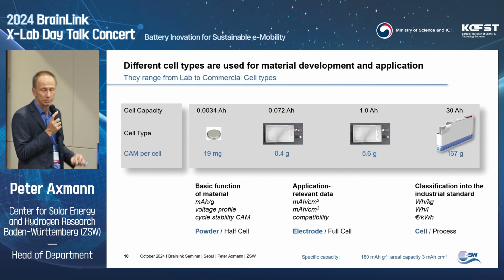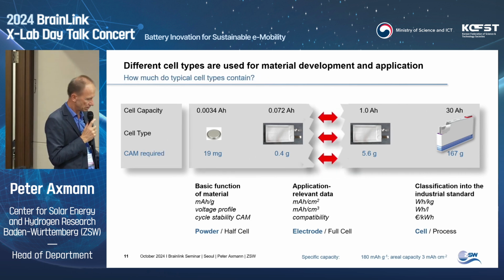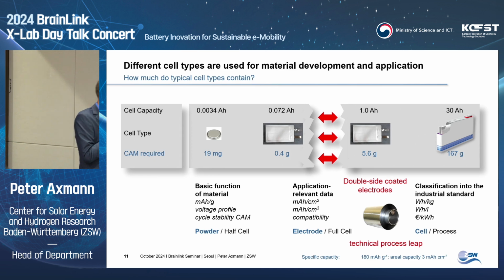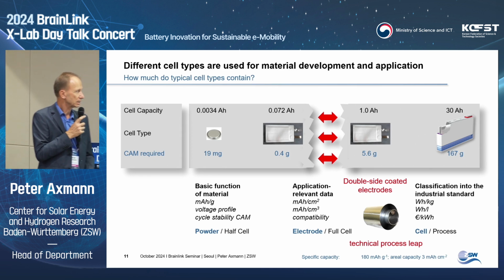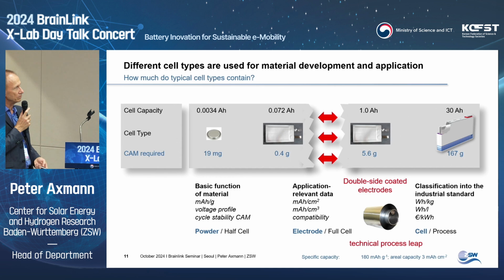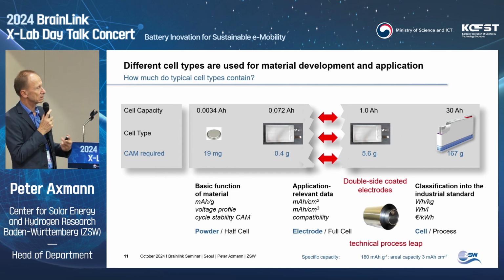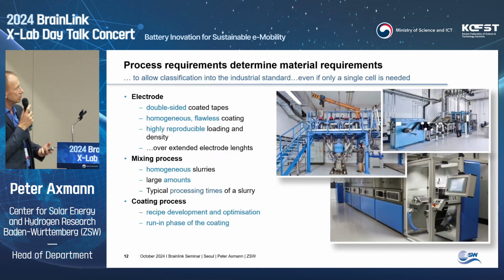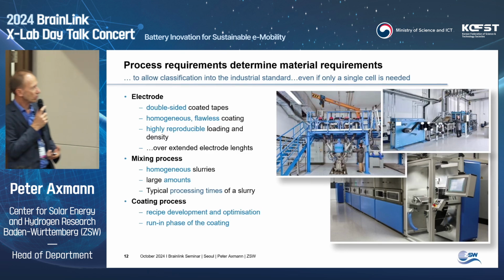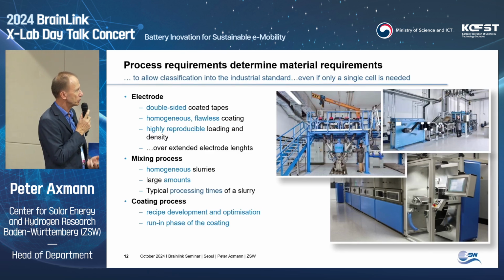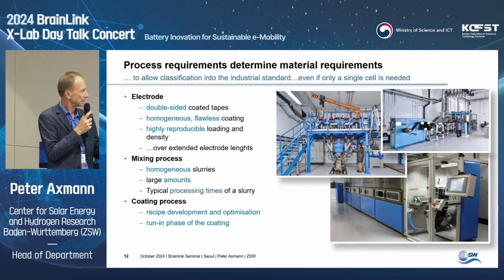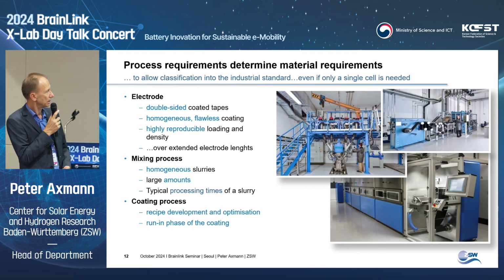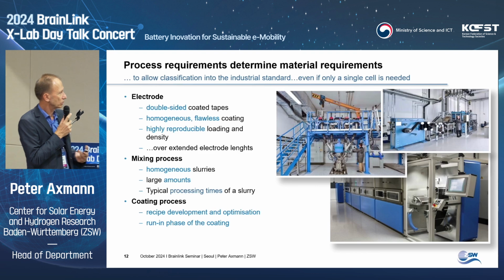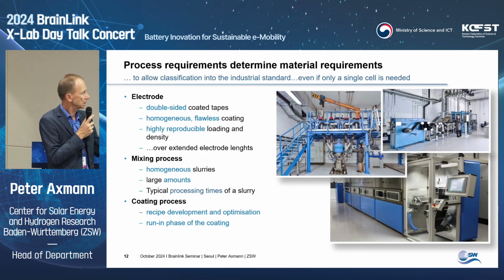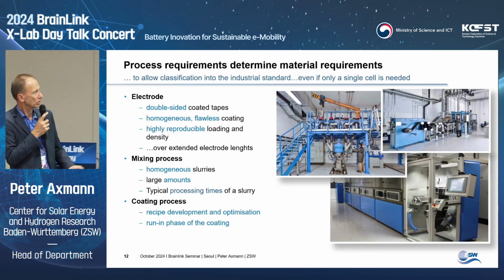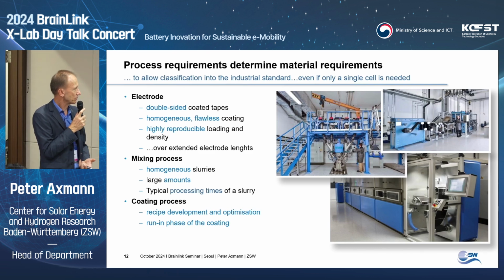But the problem is you cannot make such a battery in a lab, because you have here a technical process leap: you need to go to double-side coated electrodes. So even for a 5.6 gram cell, you need a lot of material to go there. The reason is you need a homogeneous, flawless coating. You need highly reproducible loadings and density of both side coatings on the metal foil. And this you need extended over several hundreds of meters of electrode length. You can see here how large the machines look which you need to make such types of cells.